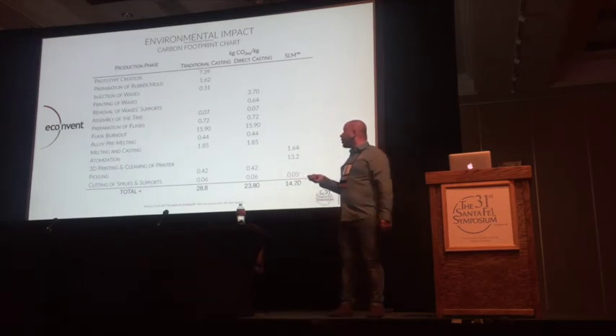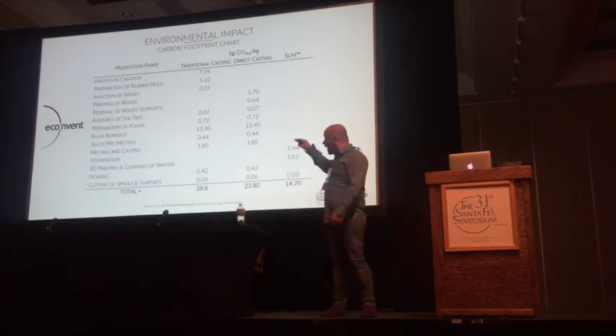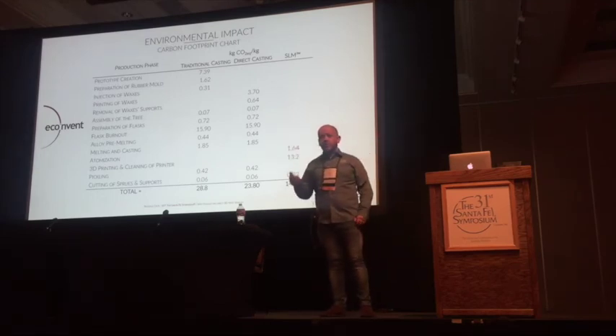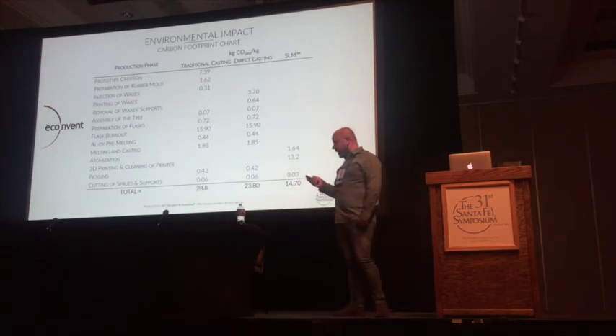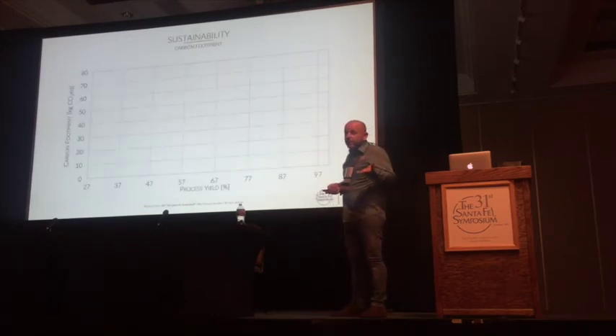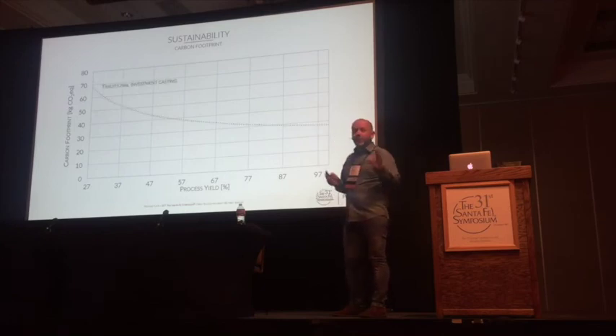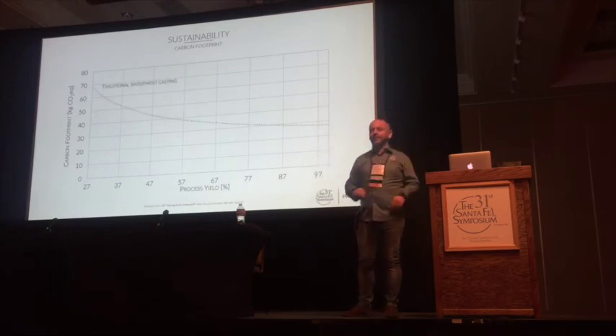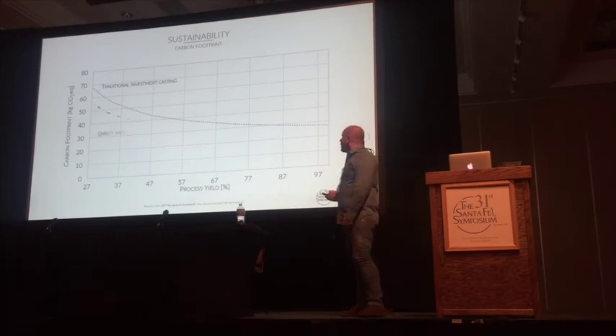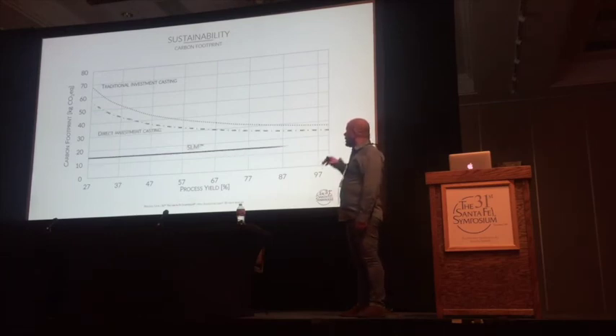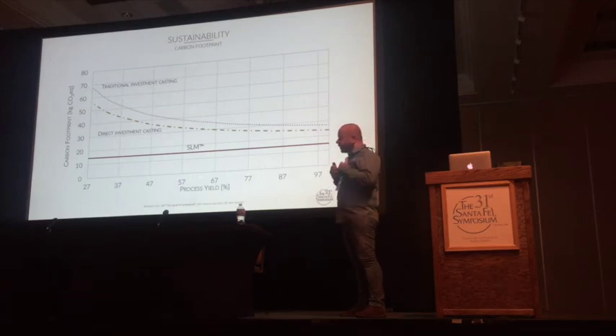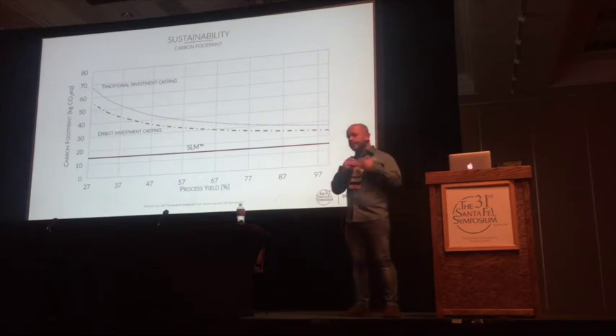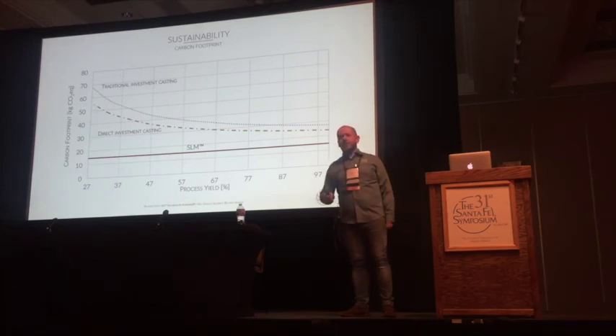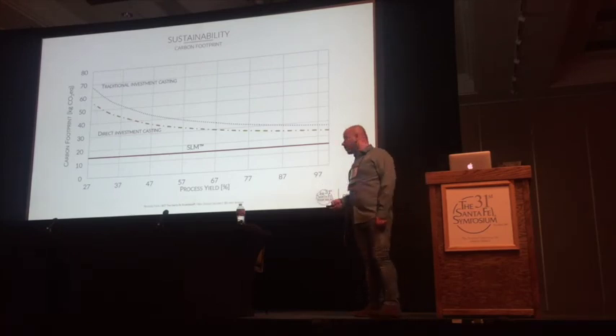So we were using the Eco Invent database. There were every single phase the calculation to do to calculate the quantity of CO2. At the end, I was expecting something better. But really also the 3D metal printing is not so green as I expected. You can see here, it's lower, but not much lower. I would say that in case of casting, we should stay at this process yield, because main companies, they less use the production capacity of their equipment.